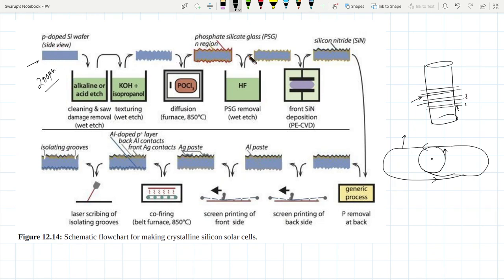Now after getting this wafer from the sawing process, when you saw it, there will be a lot of silicon dust, a lot of rough surfaces. All debris will be there on the surface, so we have to clean it off. For this cleaning process, we use two types of etching process. One is called alkaline, in the sense more basic, and another is called acid etch, acidic. So depending on the pH level, we can choose these two etching processes. So what we are doing now is cleaning off the saw damage by using this wet etch technique. And next we do a texturing process.